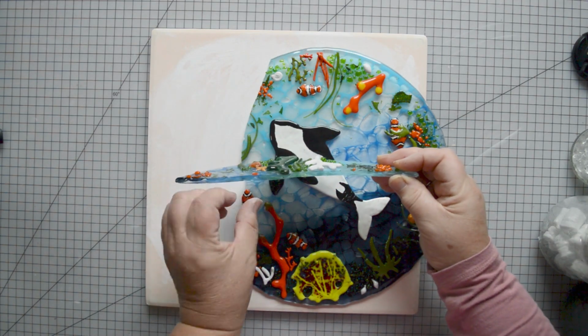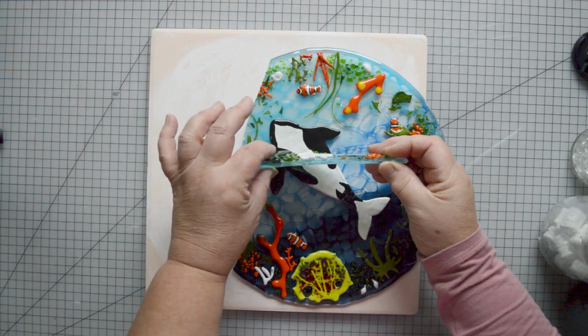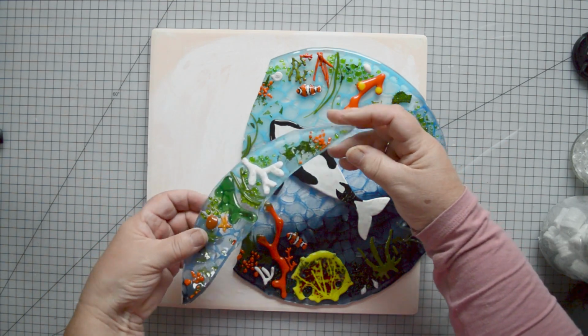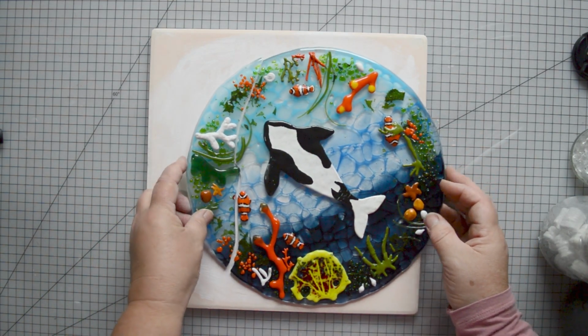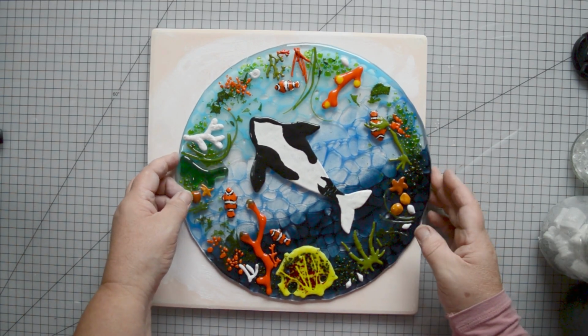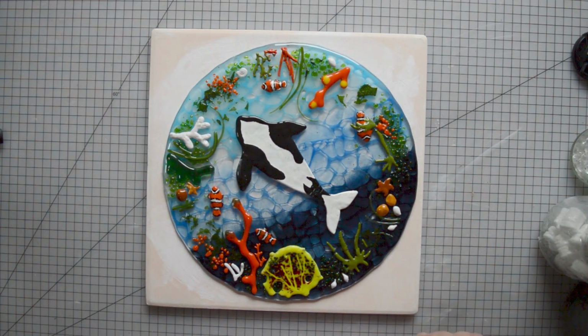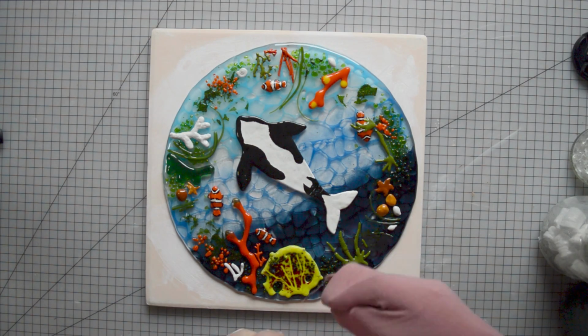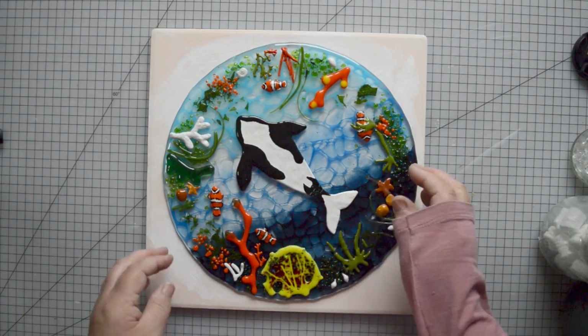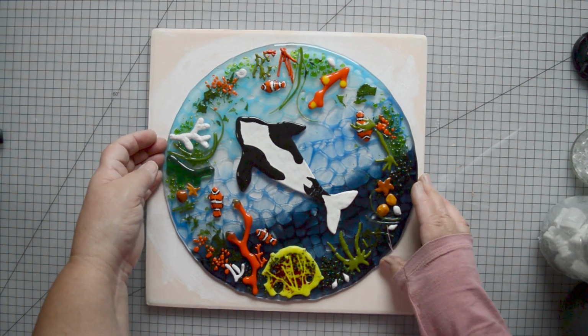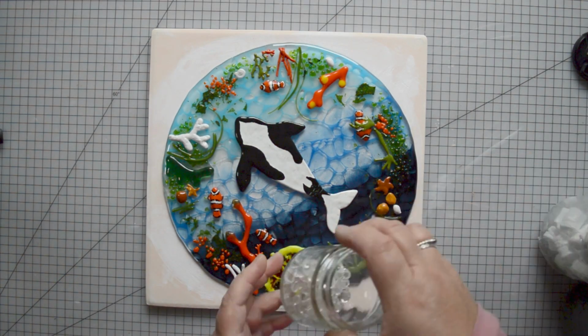All those different thicknesses of glass, I should have been much more prudent bringing the temperature back down. I think the thick green piece of seaweed caused the problem. The glass in that spot was probably near to 9mm in total. So I'm going to try and repair it, putting confetti glass and clear glass pebbles over the crack. Then it will be fired again using a sensible tack fuse schedule.